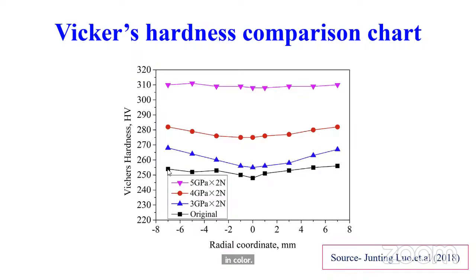The hardness is measured on the radial coordinate of the samples, which are processed with 5 gigapascal and 2 passes, 4 gigapascal and 3 gigapascal, and the original sample. You can see this original sample is black in color. The hardness of the original sample is in the range of 250 to 260 Vickers hardness. Whereas if you see the material processed with 5 gigapascal and 2 passes, you can see the difference in the hardness. Almost homogeneity is achieved in the hardness, so we can see that almost the line is straight.